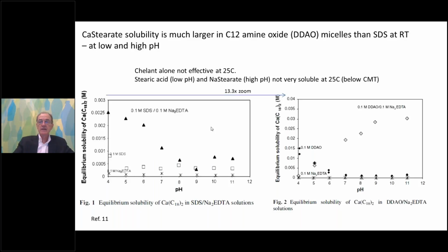So let's look at the equilibrium solubility of calcium stearate as a function of pH and surfactant type. We have here on the y-axis the equilibrium solubility of calcium stearate for two different systems, one based on SDS on the left and one based on amine oxide on the right. And we see in the details of the plot that just 0.1 molar EDTA doesn't do much. SDS alone also doesn't solubilize very much calcium stearate. But when we have the SDS and the EDTA combined, now we can begin to actually solubilize that very insoluble calcium stearate.